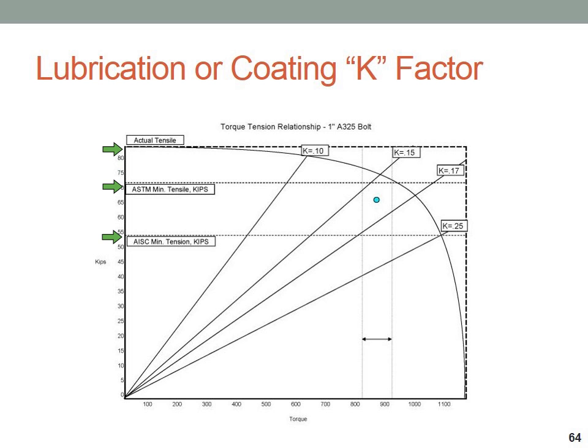Nobody makes their bolts right at minimum, so if we took a typical example of a bolt that is quite a bit above required minimum tensile, this line that goes along here would be representative of a very low K factor of 0.10. You can see that for very little torque input, we can gain a high level of tension. What's important to see in this is that this curve that sort of follows along here is the strength that can be reached at any one of those given K factors.